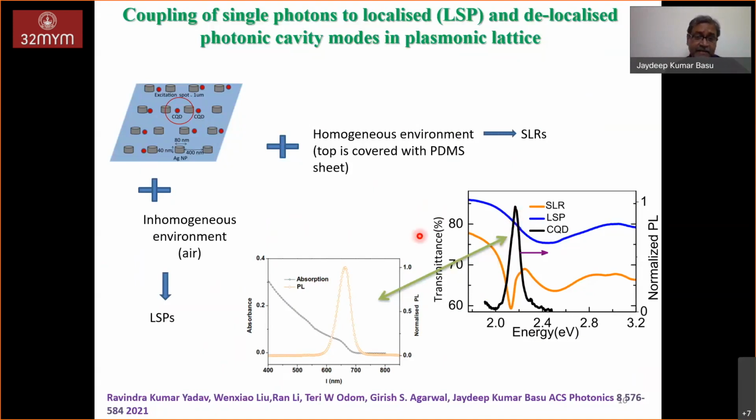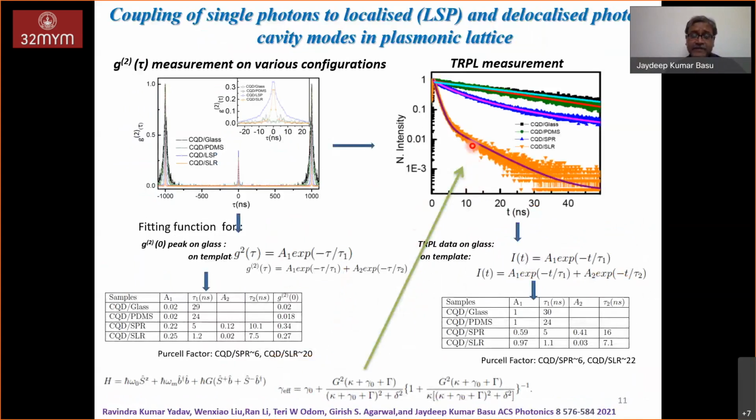But when you look at something different, which is when you measure the lifetime. These excitons, when these electrons are excited, they will come down after a certain time, so there is a lifetime they have. When you measure that lifetime of these excited states, what you find very interestingly is this: this is the data for lifetime where it is not on the lattice, but just the isolated dots. When the lattice mode is turned off, but you have only the individual silver cylinder, which is giving the localized plasmon resonance, you see a slight change in the lifetime, which you can fit to an exponential function.